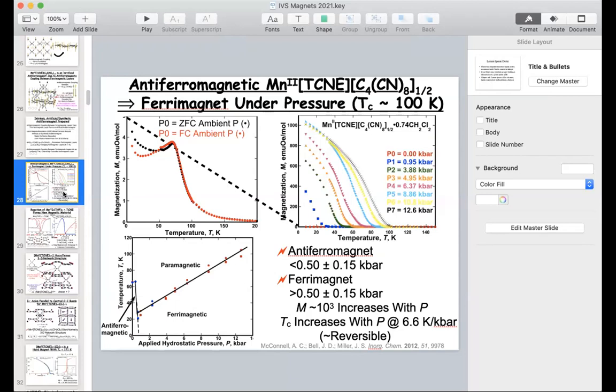We, in fact, have made lithium TCNE, not to get away from TCNE, which does not even have oxygen in it. And lithium is lower atomic mass than even carbon. And it magnetically orders as a weak ferromagnet at 21 Kelvin. And you can make other examples of it to do that. And we can make other organic radicals, hexacyanobutadiene or TCNQ, radical anions, and make magnets out of it. The fact of the matter is the TCNE analogs of any of the other ones, they're simply more plentiful and higher ordering temperatures. It works better. But there are other examples we and other people have made.